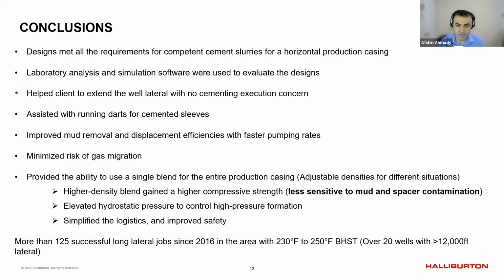And also with those changes, we could eliminate the lead entirely and use just single cement design, because ECD was not really a concern there. And we could have just one cement design to be used for long lateral one. And that helped with logistics. First of all, it's safer. And you could have the higher density in the vertical section, ending up with higher hydrostatic and less requirement for backside pressure when you have concern with the high formation pressure.